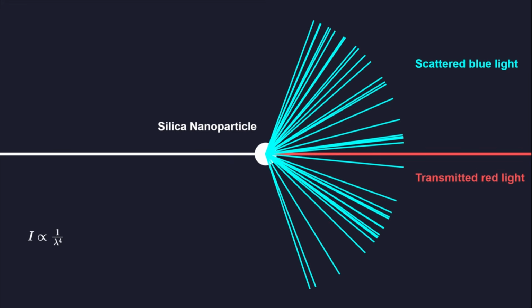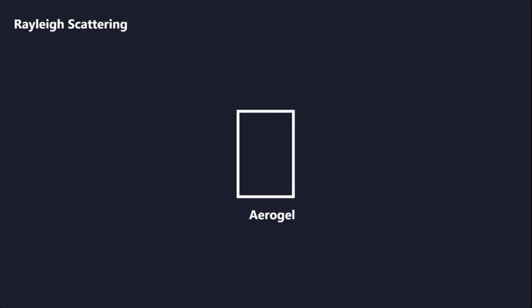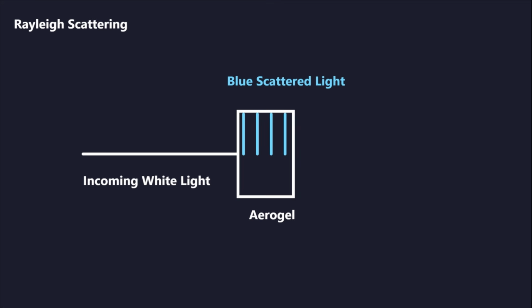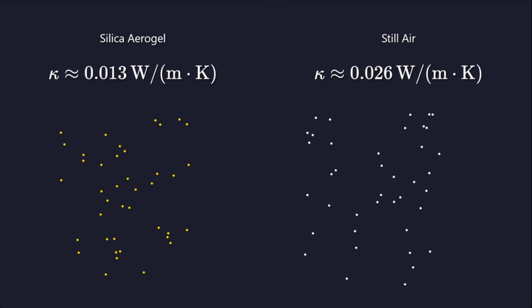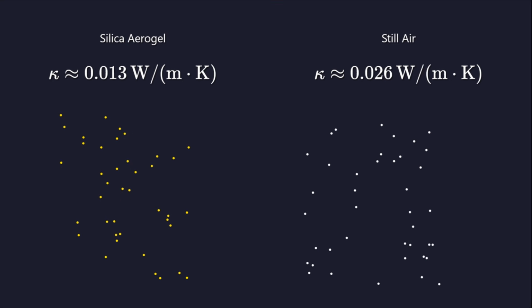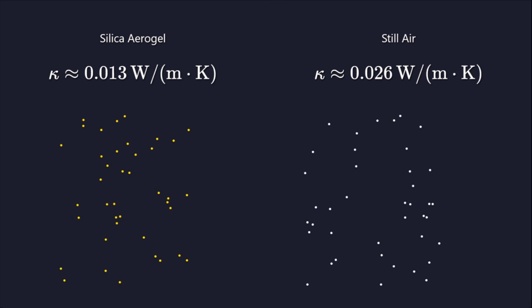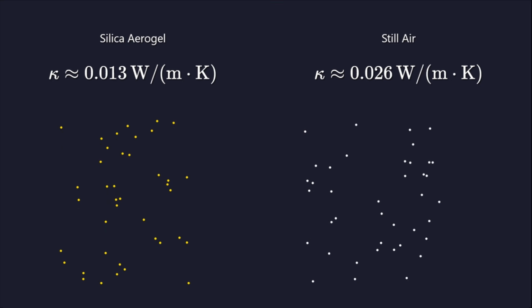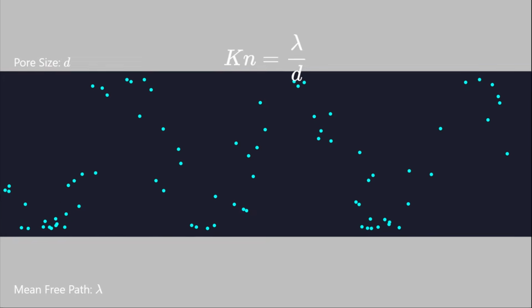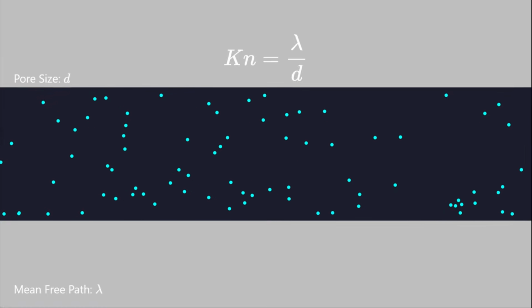The blue color arises from Rayleigh scattering, where the tiny silica nanoparticles scatter shorter blue wavelengths more effectively than longer red ones. This explains why aerogel looks blue against dark backgrounds, but casts a yellow or orange shadow when light shines through it. Silica aerogel has a thermal conductivity as low as 0.013 watts per meter Kelvin, lower than still air.